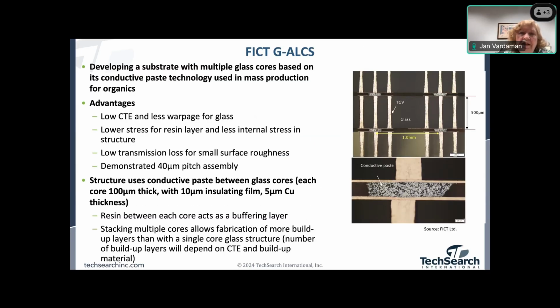So FICT is basically developed a substrate with multiple glass cores that's based on its conductive paste technology. Some of you will remember the ALIVH process, where they used basically a resin, a conductive paste between the layers. And so that's what they've applied to this. They say the advantages are low CTE and less warpage for glass, lower stress for the resin layer and less internal stress in the structure, a low transmission loss for small roughness, and they've demonstrated 40 micron pitch assembly.